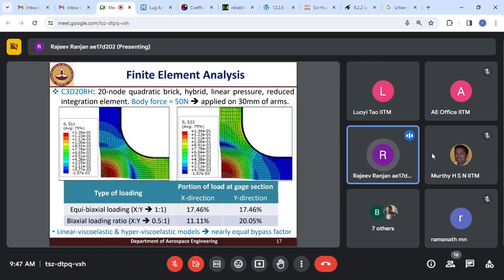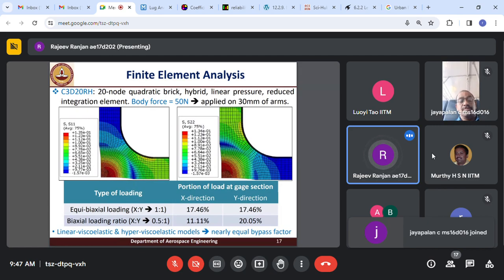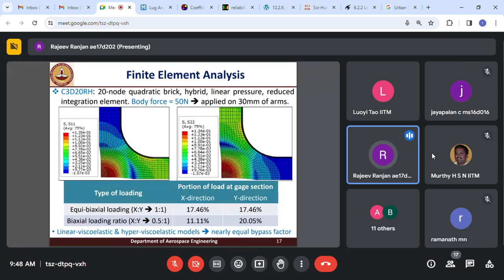Based on this FE analysis, we observed that the bypass factor for equibiaxial loading was 17.46% in both x and y directions, and for biaxial loading with a loading ratio of 0.5:1, it was 11.11% in the x direction and 20.05% in the y direction. We also conducted this FE analysis by considering a linear viscoelastic model, and a nearly equal bypass factor was observed.